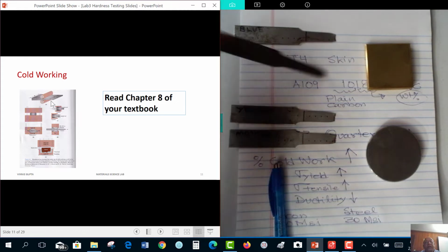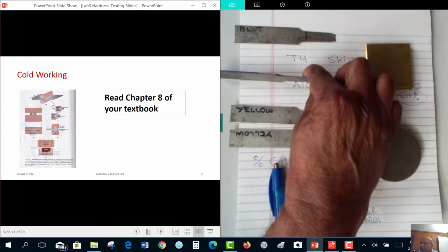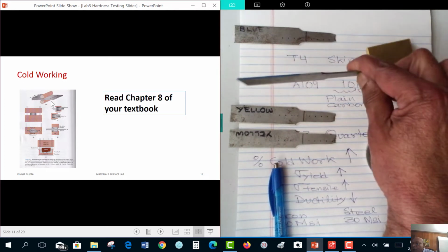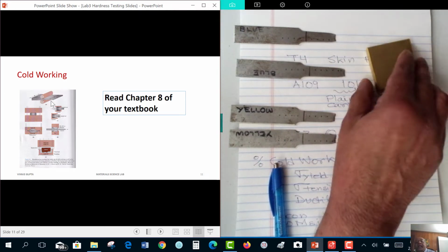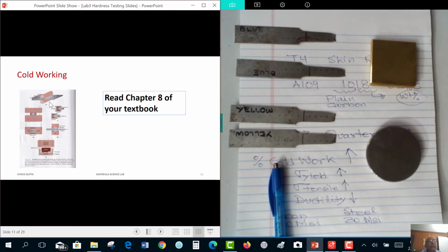Basically, what we do is we take a thicker sheet and pass it through the roll so it decreases its thickness, just like as is shown schematically here. So what we are doing is we are reducing the cross-sectional area as we go through each rolling pass. Another way we can do it is we can compress it, cold deform it, do a cold forging or a die forging. We can also do extrusion, push the material through a die as in extrusion.